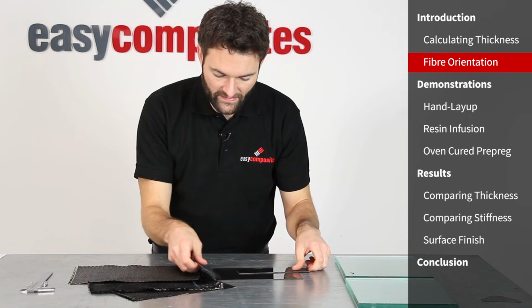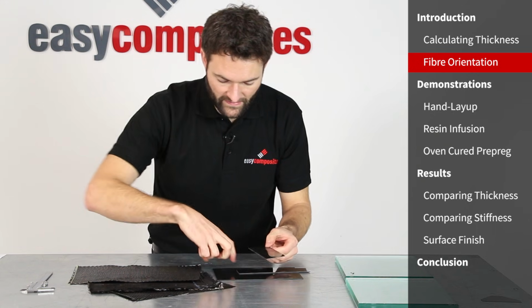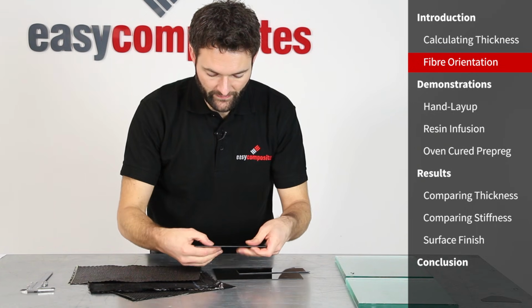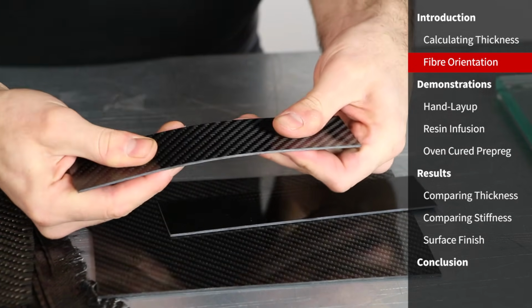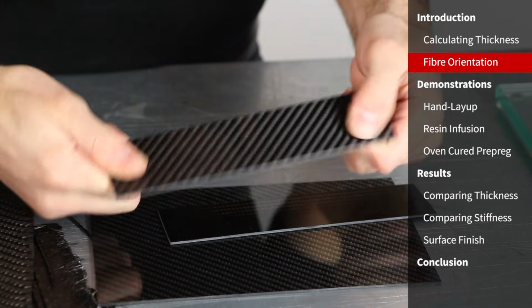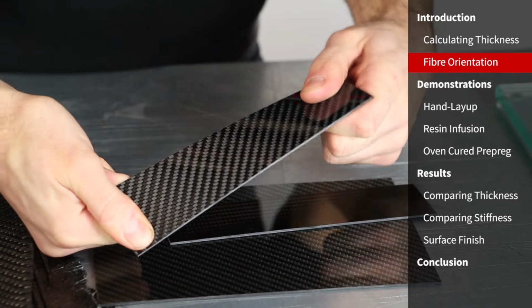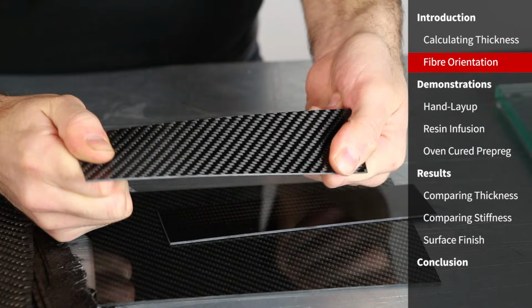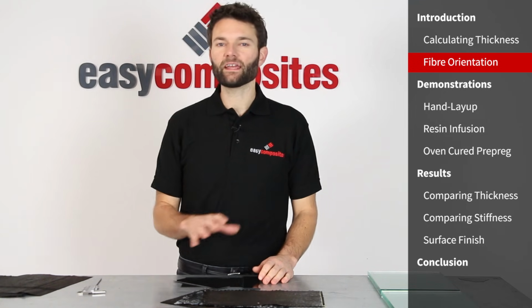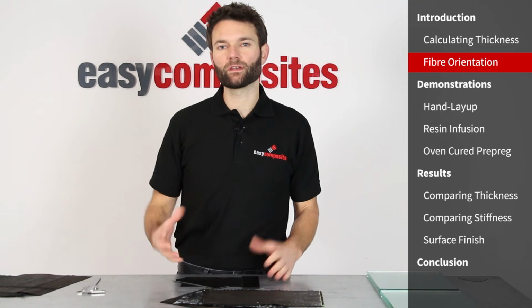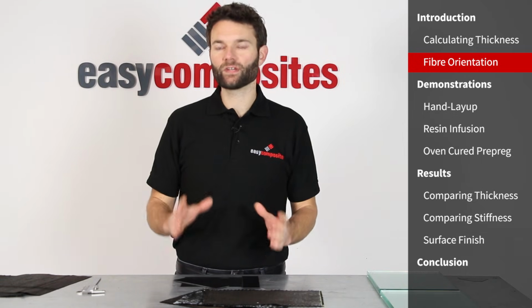So if we then take the other piece that's been cut at 90 degrees, so straight across the sheet, in that direction, very, very stiff. But if we try and twist it, its torsional strength is far, far less than this one cut at 45 degrees.